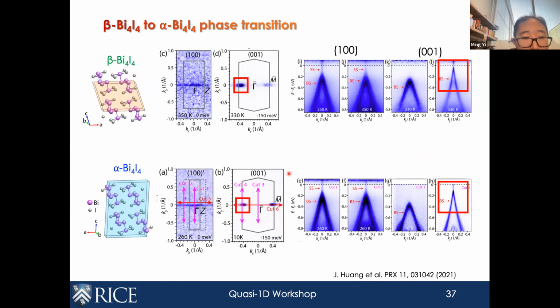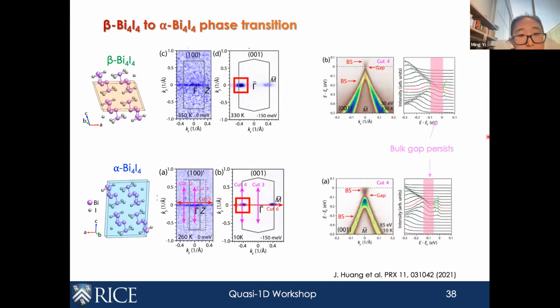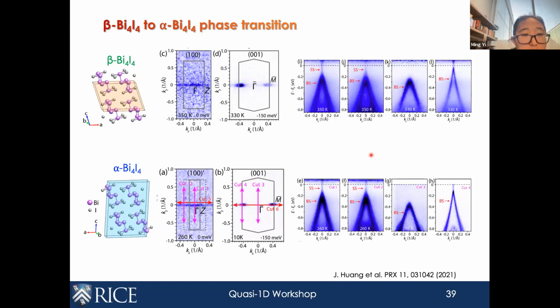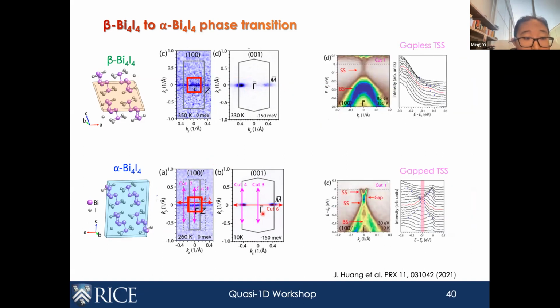So if we look first at the trivial 001 surface here, zoom in here to this bulk band gap, the bulk band gap remains after the band doubling, so nothing changes in topology here. But the interesting thing is that if we look at the 100 surface where the Dirac points reside, while they are gapless in the beta phase, we do observe very clearly the opening of a gap in the topological surface state.